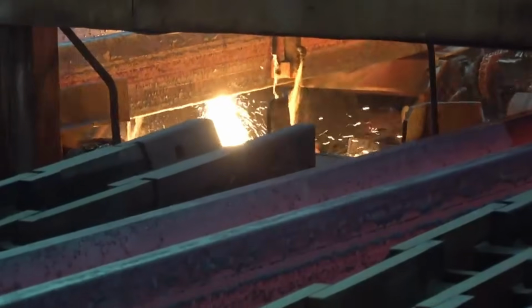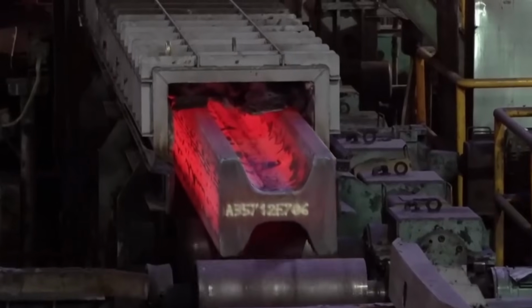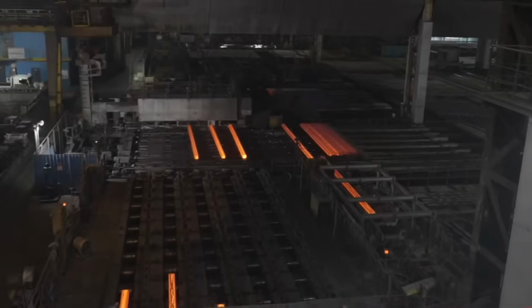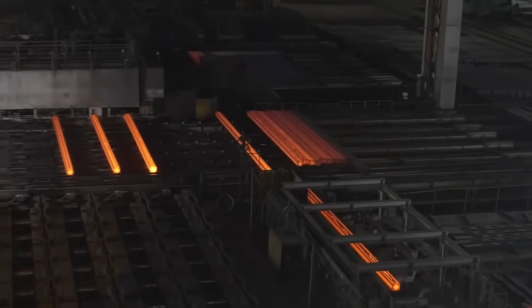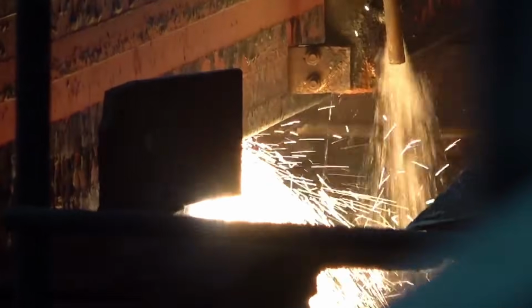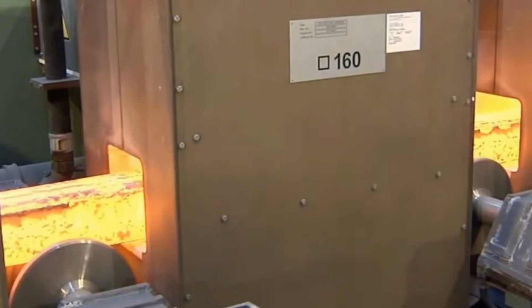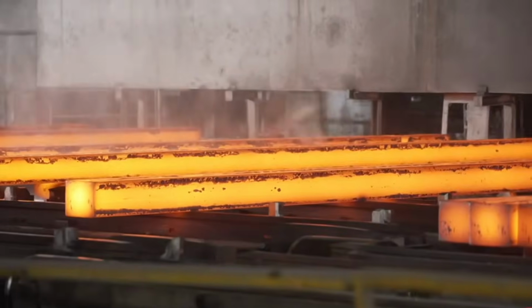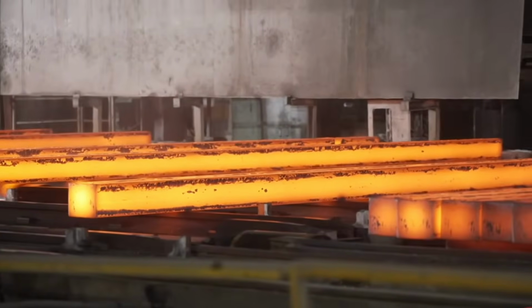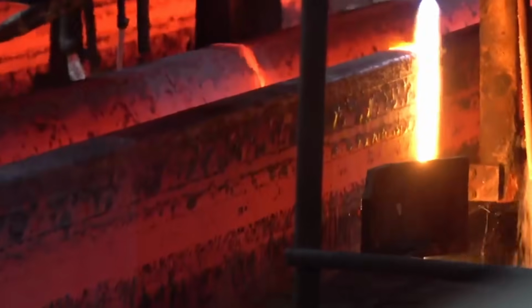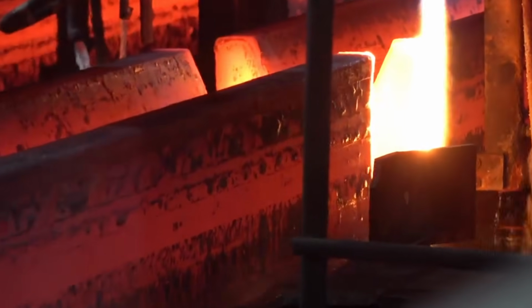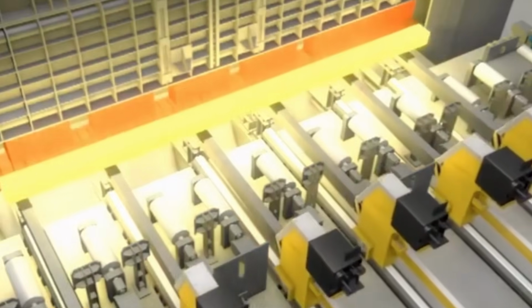Below 1,000 degrees, beams enter heat treatment for final strengthening. Quenching with water or oil creates harder surfaces while interiors remain ductile. Tempering follows, reheating to 800 to 1,000 degrees to relieve stress. Exact treatment depends on intended use. Earthquake zone beams receive different treatment than cold weather beams.